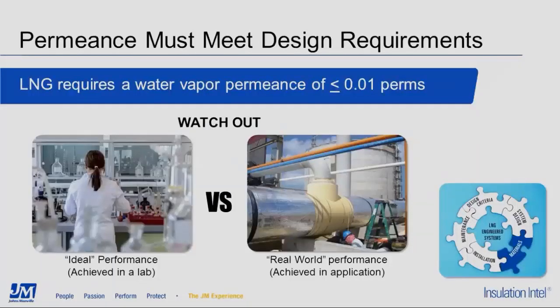The typical requirement for the vapor retarders on an LNG pipe insulation system is a permeance of less than or equal to 0.01 perms. However, watch out for ideal lab performance compared to actual real-world field performance. There are vapor retarder materials which might have a lab result of 0.01 perms with no joints present and in pristine lab condition, in the carefully controlled flat test geometry, but which would not work well in an actual LNG application due to the rugged environment and the presence of so many joints.